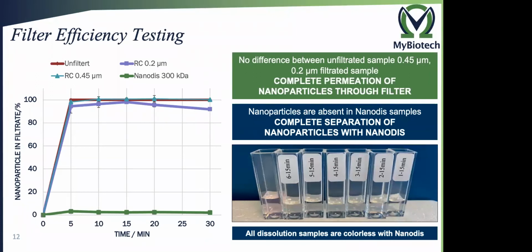On the left side, you can see the results of the dissolution study. There is definitely no difference between the unfiltered and filtered through 0.45 micrometer filter, which was as expected since the highest particle population that was present in the sample was 200 nanometers, so every particle goes through the 0.45 micrometer filter and you don't see any differences.